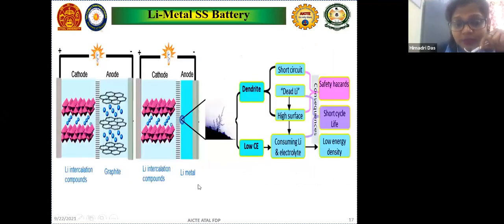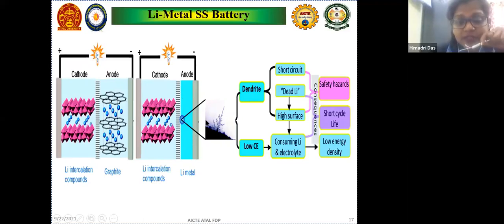So here is a picturization of lithium dendrite growth. Here a small picture I have given. So I think one can understand how the lithium gets dendrite growth. When we just use lithium metal as anode, we can see that on the surface the lithium metal dendrite will be grown. Like the problems we can face in lithium metal battery, when we have a lot of advantage of increasing the energy density or increasing the capacity, but still these are the issues faced by the researchers, like there is dendrite formation or low coulombic efficiency.